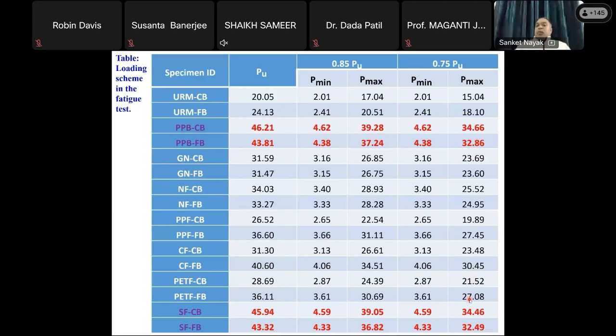PET fiber has not performed badly either, because in the case of the unreinforced one, the ultimate load is 20. In the case of PET fiber, you can see it is 28 for the clay brick and 36 for the fly ash bricks. So from 20 to 36 is a good amount of strength increase.